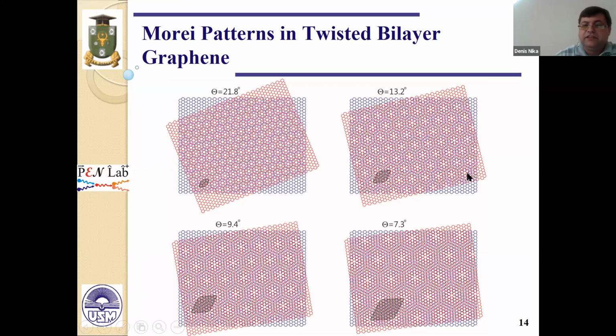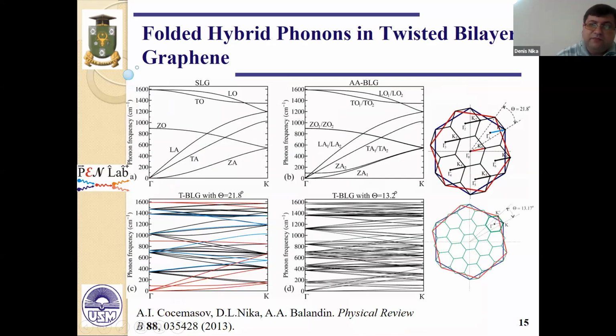You can see here in the slide different commensurate patterns with different twisted angles: 21.8, 13.2 degrees. One important consequence of the rotation on phonon states is an increase of the unit cell volume. Therefore, in the case of twisted graphene, the number of atoms in the unit cell depends on the rotation angle and is larger than that in single layer graphene.